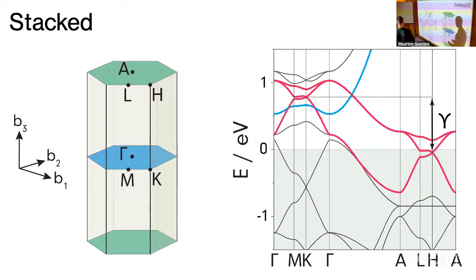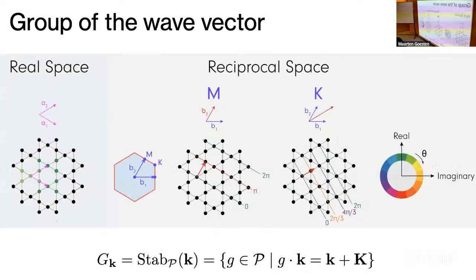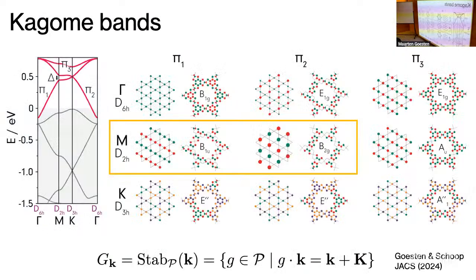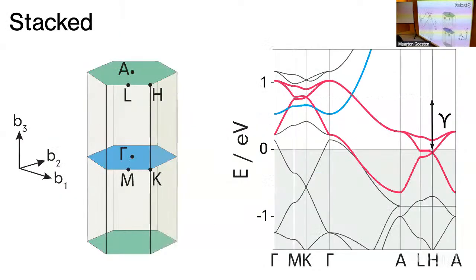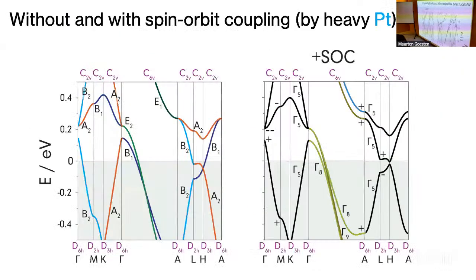What I need you to see here is that this gamma is the stabilization that we obtain due to the stacking. What happens then is that this shifts the crossing very near the Fermi level. Also, because this gap is very small and because this is symmetry protected, this must necessarily be very flat. Now, this is what we obtain.